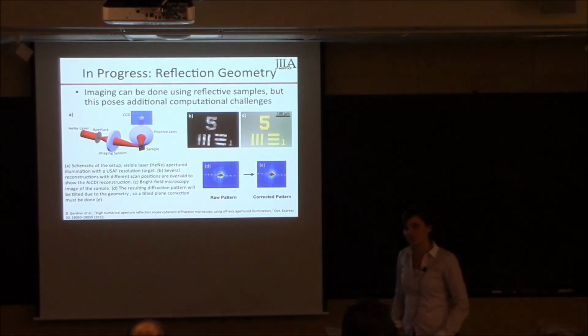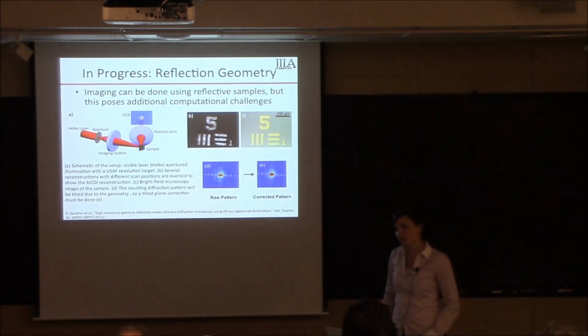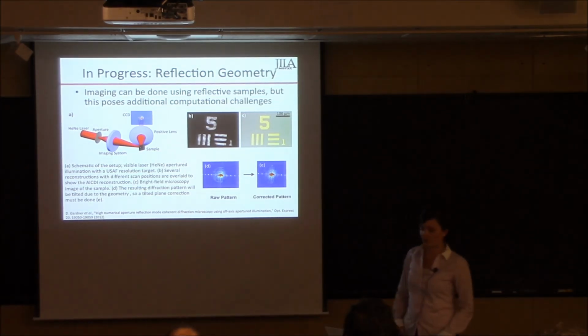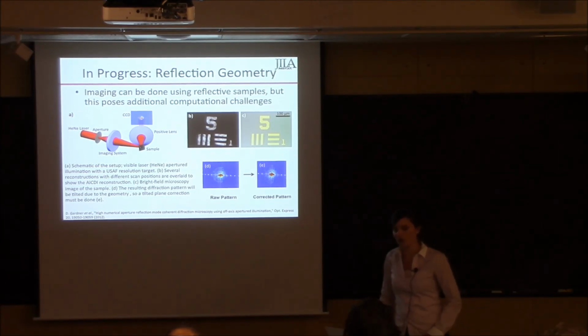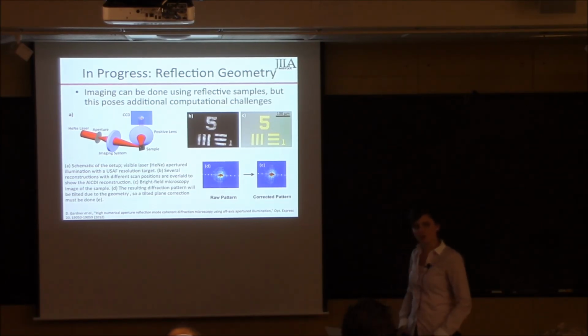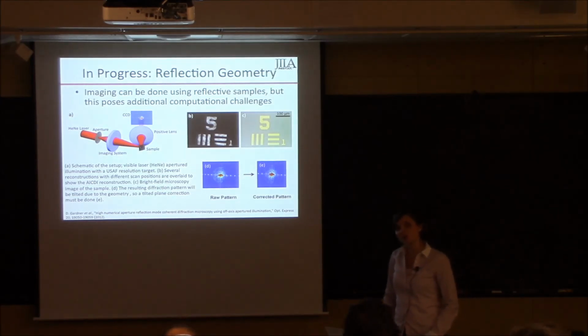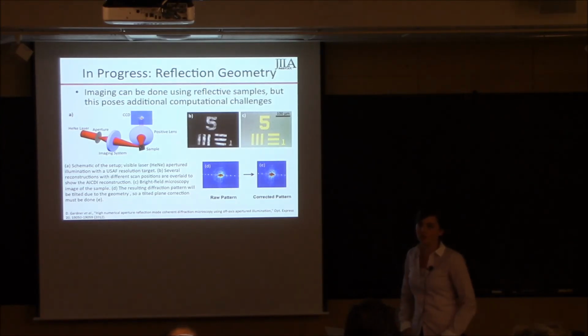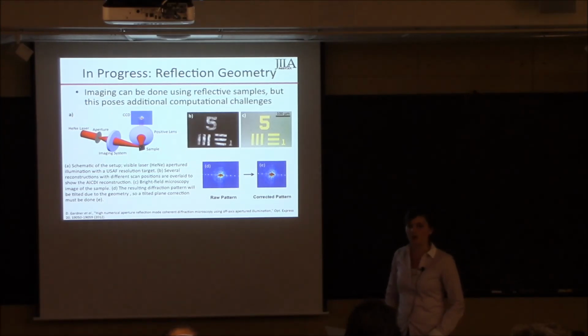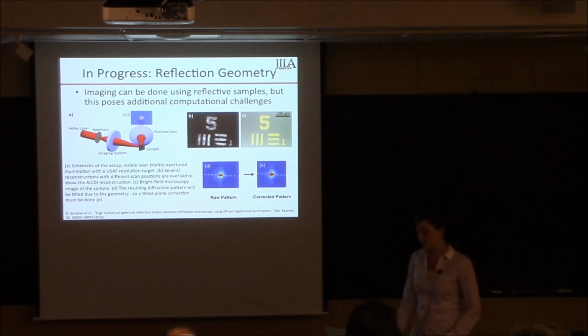What kind of image sensor are you using, and what are the pixels? So that depends exactly on the experiment, but we use an Andor CCD, which has, I believe, pixels of 13.5 microns, and it has about 2,000 by 2,000 pixels. And the exact distance of the sample varies. It partially has to do with how we align it, but for reflection mode, I believe the distance is on the order of maybe 6 centimeters.